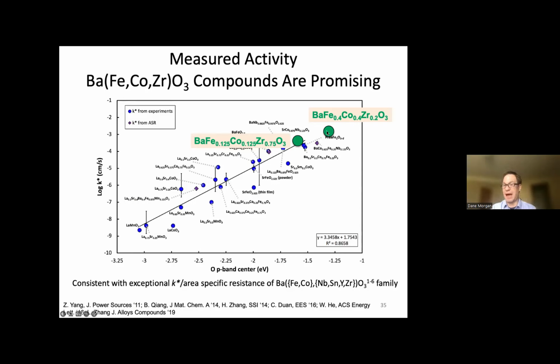We were very happy to find that the surface exchange coefficients that were measured fell essentially right on the line that we had actually predicted. So these have some of the highest surface exchange coefficients of any materials that people have ever discovered, and at least at the 75% composition, have really quite good stability. So we're excited about these as potential future solid oxide fuel cell electrode materials.